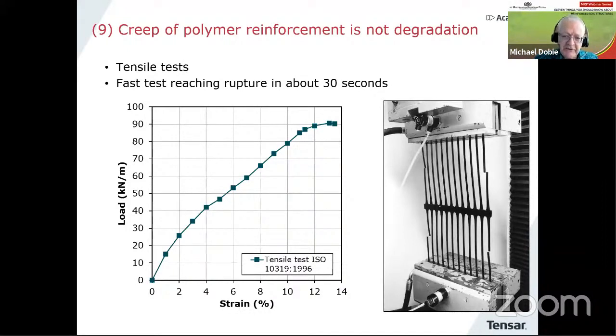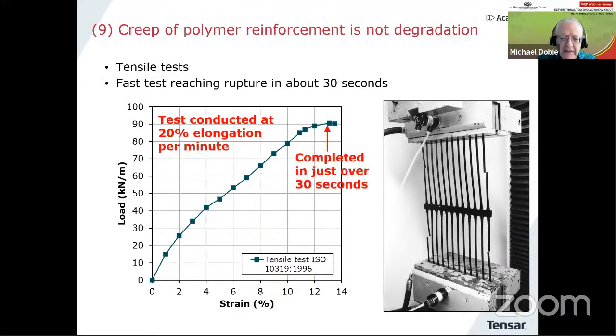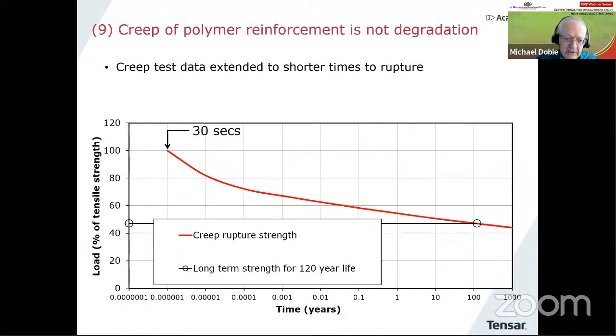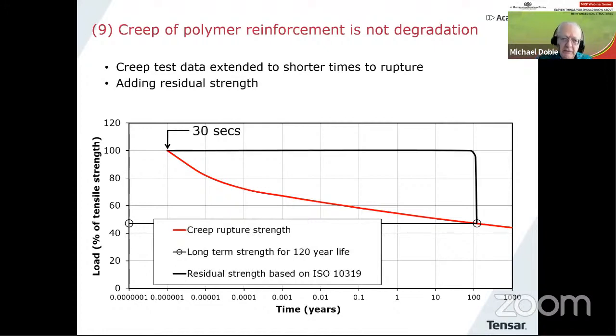And tensile testing, this is a typical test using the ISO standard, where the rate of elongation is 20% per minute. So this one finishes in about 30 seconds. So we can add that kind of information to the diagram like this, and that's where it would come. So if we call that 100% of tensile strength, then that occurs at 30 seconds, and we get now a more complete relationship. But we can add another line here, which is called the residual strength.